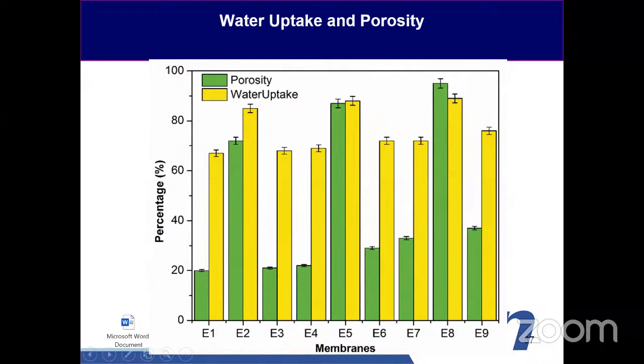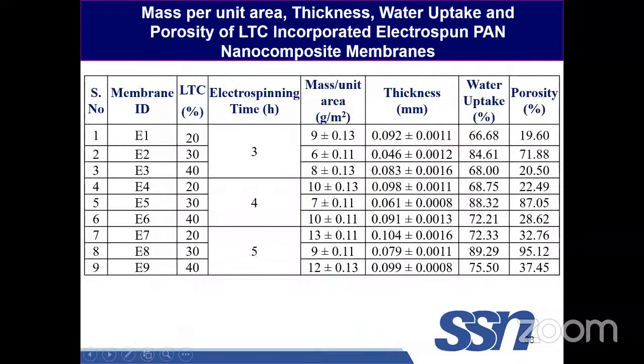Later on, we checked the different process parameters of the prepared nanofibers, like the GSM, the thickness, the water uptake, and porosity of all the membranes. As you can clearly see, with increasing time, the thickness of the material increases, and as the fiber size is quite less in case of 30% incorporated LTC, in all the samples there is a decrease and increase, because 30% incorporated fibers are less in diameter. As a result, the packing density is quite high. As a result, the thickness is less in case of 30% LTC.